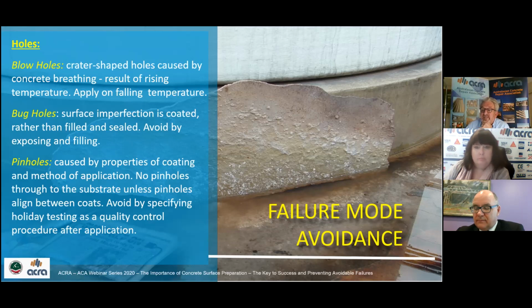Pinholes, the bane of a lot of contractors that coat concrete. These holes are small, but they're difficult to see with the naked eye. They're caused by both application properties of the coating and method of application. Multiple coats of material are applied to minimise the probability of pinholes. From one coat to another, there'll be no pinholes through to the substrate unless the pinholes are lined up between coats. That can happen.